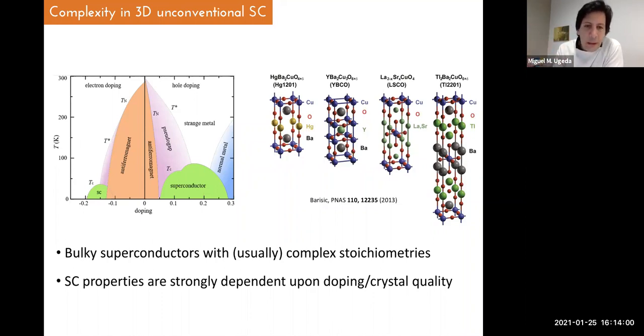The other reason is that these materials in general show a quite complex phase diagram that is extremely dependent upon, for example, doping or upon the presence of defects. And that's a challenge as well for modeling, but also if you want to grow and reproduce some results. If you're an experimentalist, it's quite delicate the way these materials have to be grown in order to make them reproducible. So that's the reason why I think this field is so complex, so difficult.